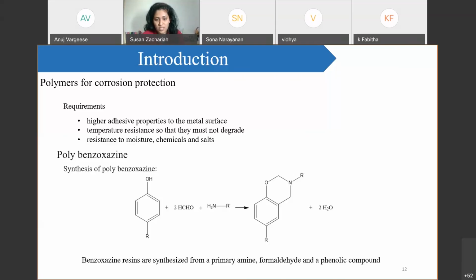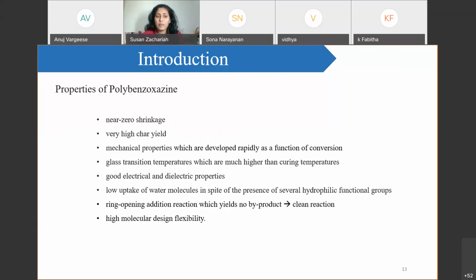This is the preparation of polybenzoxazine. It is prepared using a primary amine, formaldehyde, and phenolic compounds. The properties of polybenzoxazine include near zero shrinkage, very high char yield, and good mechanical properties. The glass transition temperature is higher than the curing temperature. It has good electrical and dielectric properties. Low uptake of water molecules, even though it has some hydrophilic functional groups. So this polymer itself will repel the water, which will enhance the application. The polymer is also hydrophobic, and we are implementing the structures over it, so it gives a bonus point because of this polymer's characteristic. Ring opening addition reaction, which yields no byproducts, a clean reaction. High molecular design flexibility.